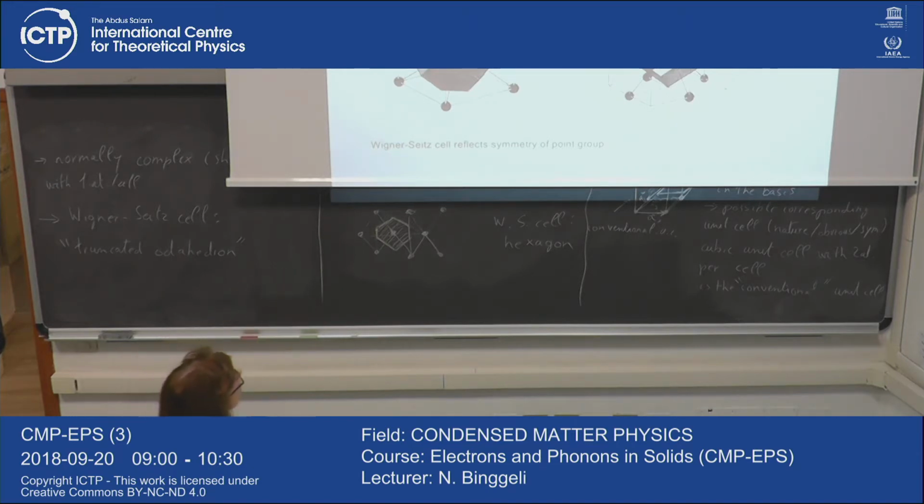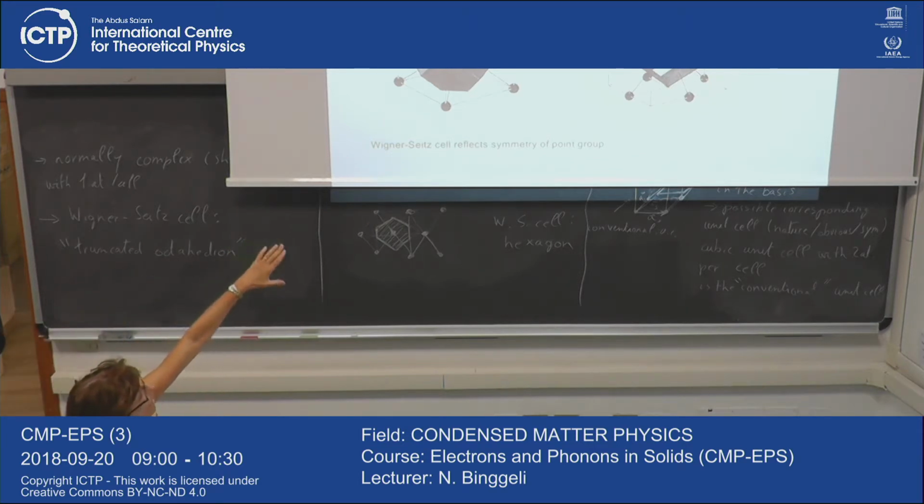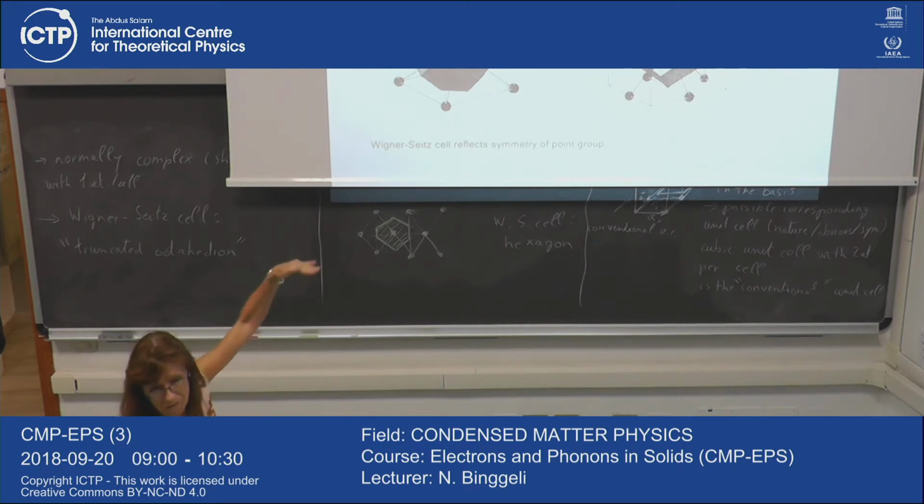these 8 hexagonal faces. And then on top, on bottom, and on the 4 sides, you can see these square faces which face the second nearest neighbors. So in the BCC, you have 6 second nearest neighbors, and so you have these 6 squares that are the facets that face the second nearest neighbors. So the octahedron, which would correspond to the planes of the hexagons, is truncated 6 times, putting these square facets that face the second nearest neighbors. So in the case of the BCC, not only the first neighbors, but also the second nearest neighbors need to be included to limit the volume of the Wigner-Seitz cell with bisecting planes.